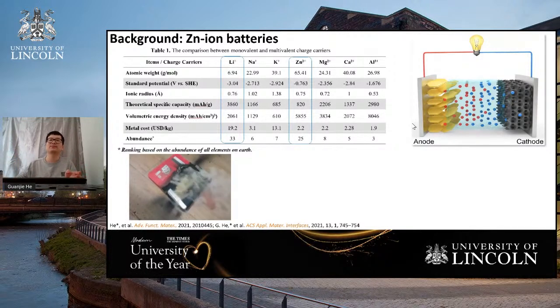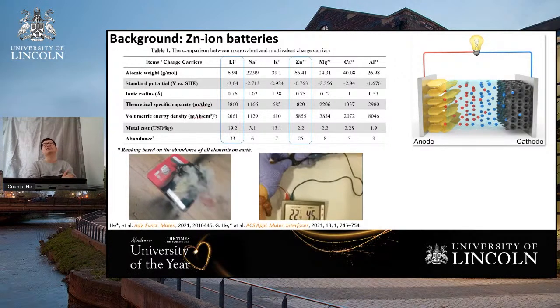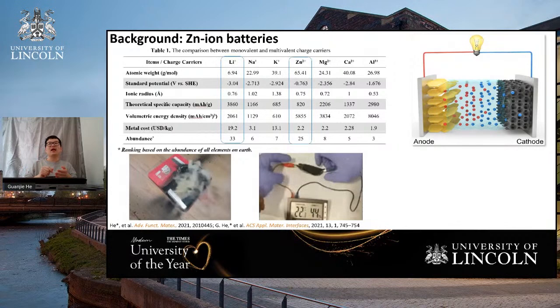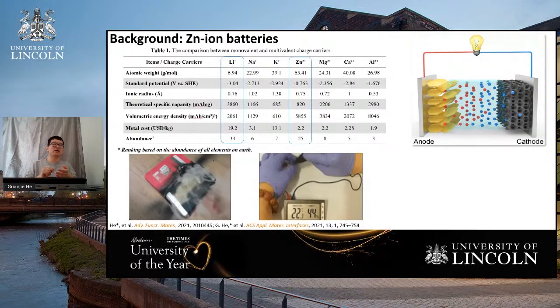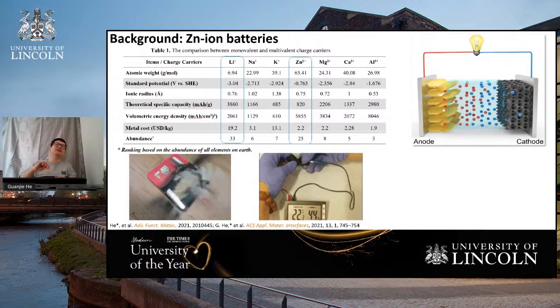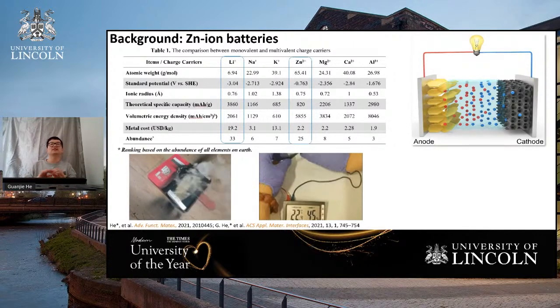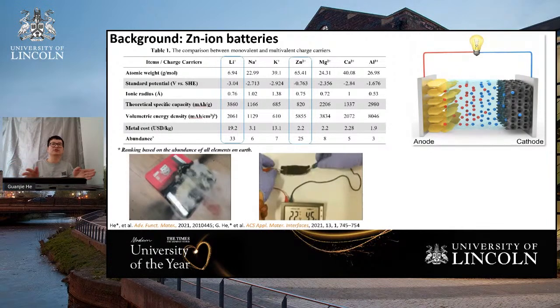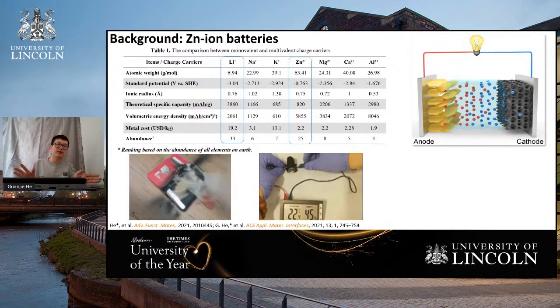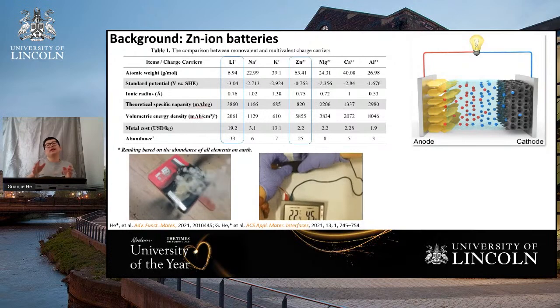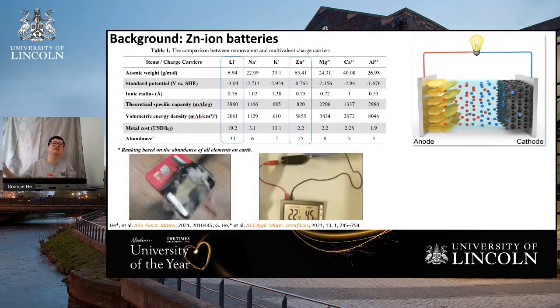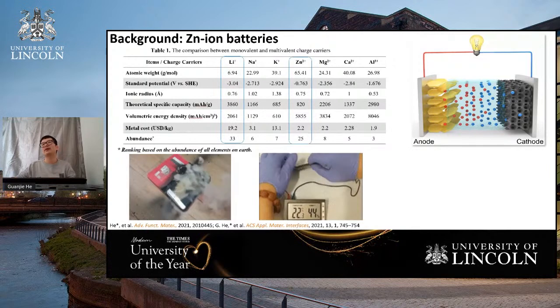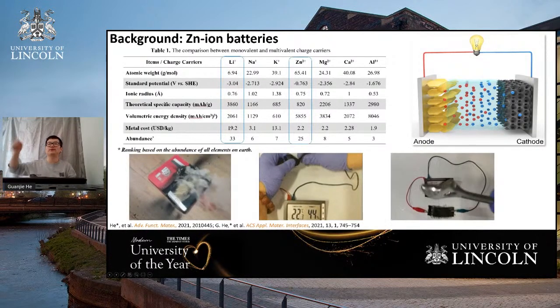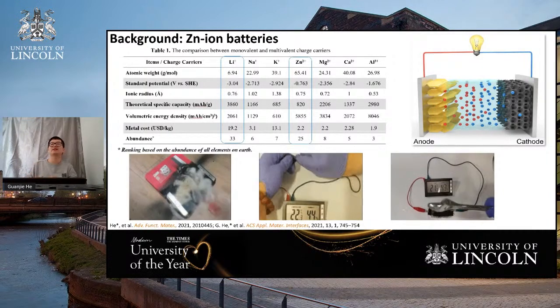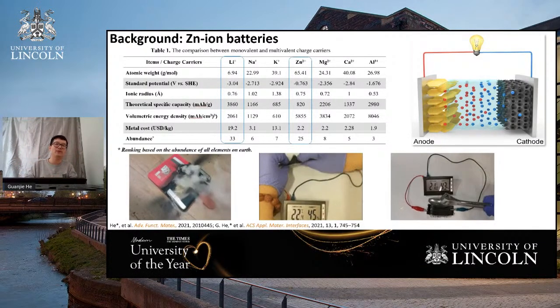So that is perfect. And our group has developed different flexible zinc-ion batteries. We use hydrogel as the electrolyte. So you can see those devices, you can easily bend it, fold it, but there's no explosion, even if there's a short circuiting happening, right? And we can simply integrate them with other flexible electronics. And we also try to use a hammer to hit it, and you can see those batteries work quite stable.